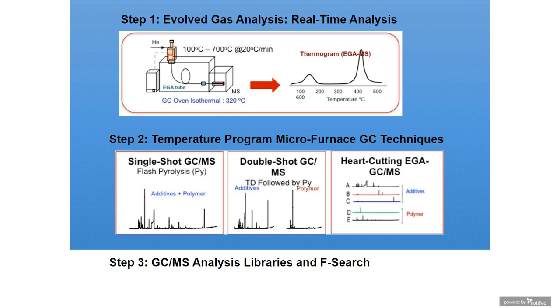And again, without reviewing much, EGA gives us the thermal map of degradation. It's very similar to thermogravimetric analysis. Single shot flash pyrolysis, based on the known temperature or degradation of the material, gives us a big distribution, or rather spectra, of the whole composition that includes the additive and the polymer. On the other hand, we can isolate the additive and the polymer by doing a double shot experiment. And with the heart-cutting, as I mentioned earlier, you can focus on specific regions and divide it into zones like A, B, C, D, and E.